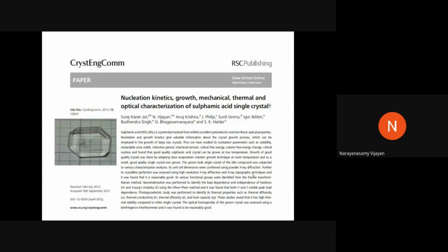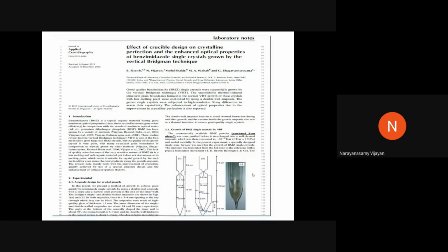And not only that, how the nucleation is forming, what is the size of the nuclei. By doing theoretical analysis, we reported this for sulfamic acid single crystals. Double wall versus single wall, what is the variation, and how we can control the defects. This also we have studied in a thorough way.